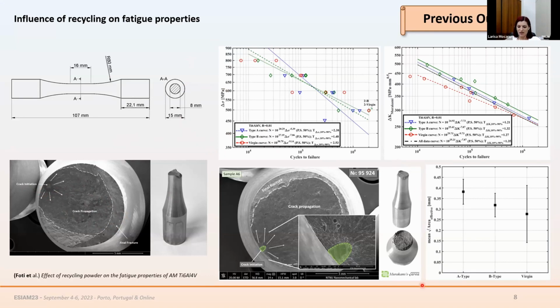We also performed a defect influence analysis according to the Murakami method, and we analyzed the external defects and also the internal defects, and we saw a slight difference in the average dimension of the critical defects, which is higher with increasing number of recycling, as can be seen here in the comparison between the A type and the virgin type. But in this case, we also saw a decrease in the data scatter, as can be seen here. But also in this case, these are preliminary results, so we need to investigate this topic better.